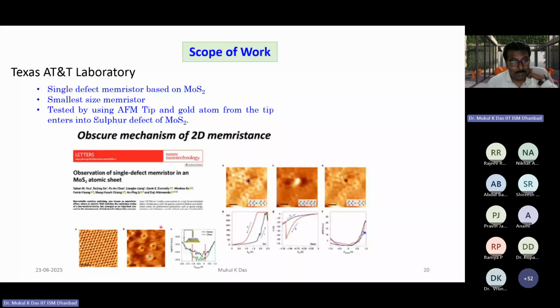This is the smallest size number, and they did the experiment simply by putting the AFM tip on the molybdenum sulfide layer. With the AFM tip, one gold atom from the tip migrates to the MoS2, and the current increases. That means after putting the AFM tip, we observe the current being increased. So this is the behavior.